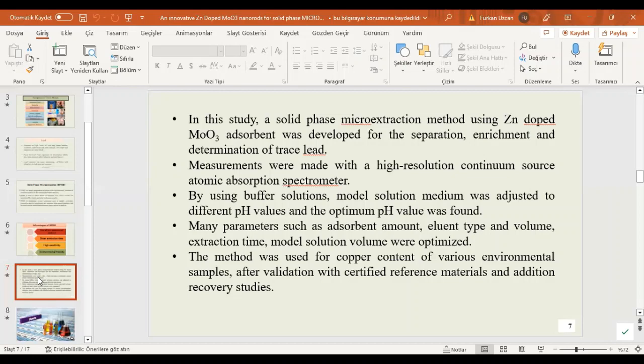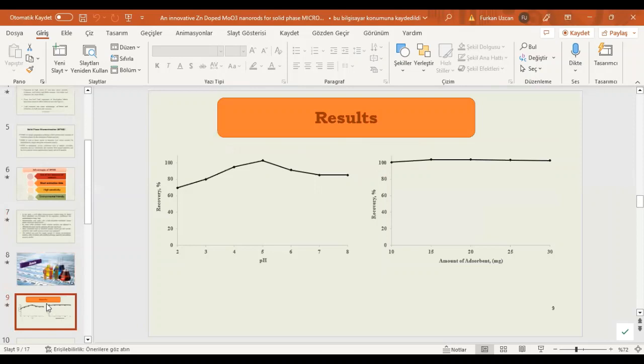Results. As you can see in the figures, the first figure is pH optimization. We studied between 2 to 8 pH. The quantitative recoveries we got at pH 5, so we selected pH 5 for further work. Next figure is adsorbent amount. We used adsorbent amounts between 10 milligrams and 30 milligrams. At all levels we studied, we got quantitative recovery. So we used 10 milligrams adsorbent zinc doped molybdenum oxide nanorods for further work.